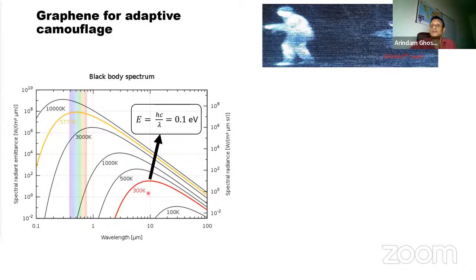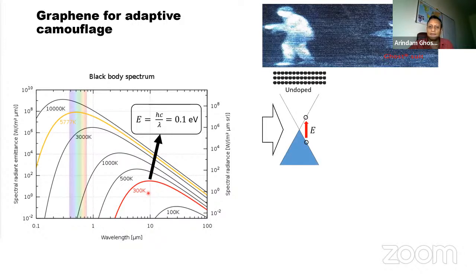Now, can one do something else so that these radiations at these 10 micrometer wavelengths can no longer get transmitted but are reflected back to the body? And this is how graphene can probably be of help. For example, if I take graphene, what happens is when I shine these waves of 10 micrometer wavelength, the electrons from the valence band get transferred to the conduction band, and it gets absorbed in graphene, and then graphene re-emits that wavelength, and that goes to the camera, and you can get imaged.